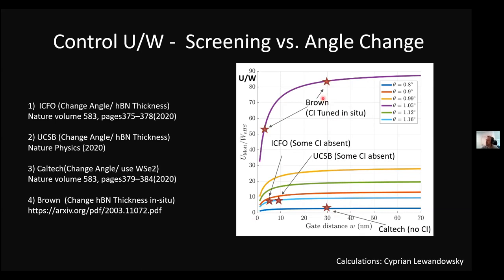So you should take this graph with a grain of salt, because it's just a theoretical calculation. Most likely the changes in the bandwidth are not as pronounced as in this graph, so probably this curve should be shifted down. But no matter how you define all these quantities, it seems that in this particular case that I'm going to talk about, this ratio is reduced at least 2 to 4 times in comparison to the other experiments.